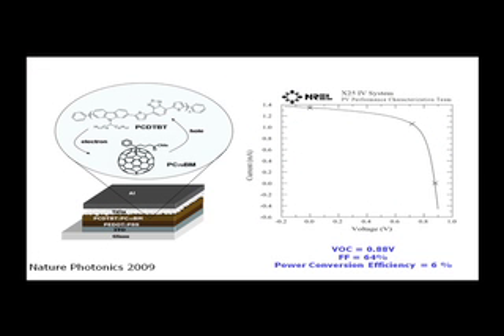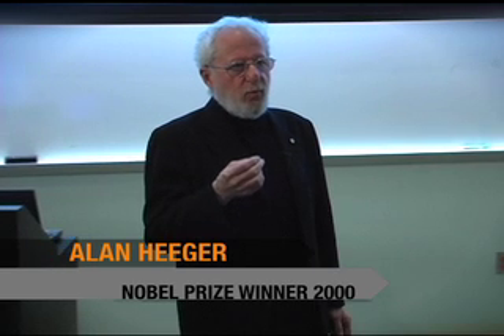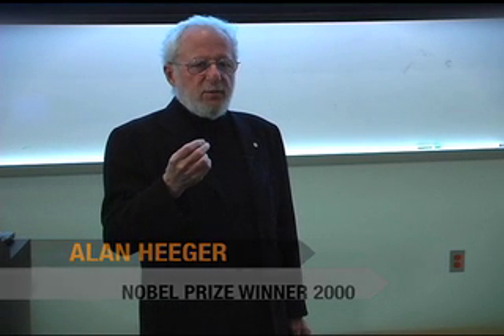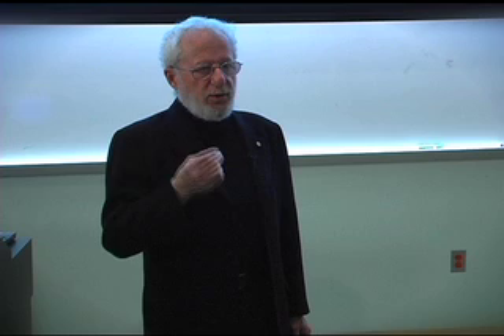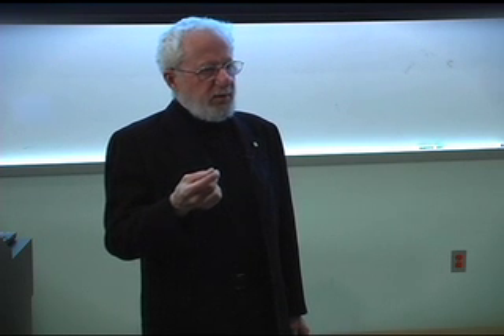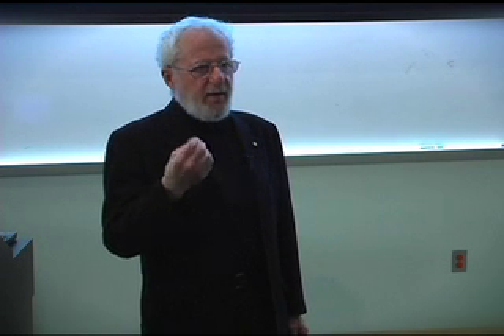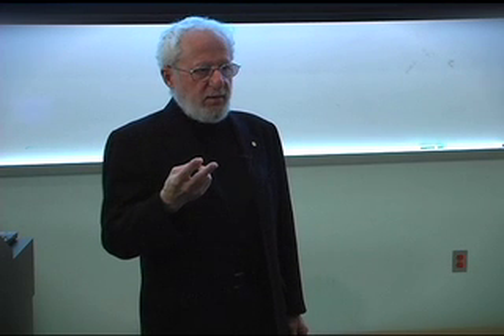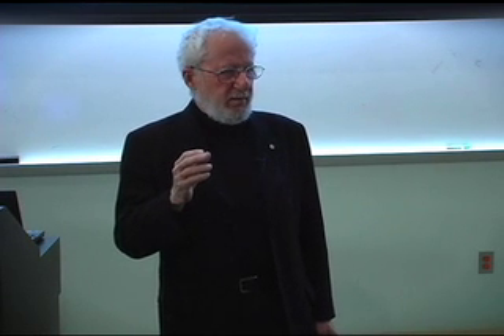Here's an example of some work that we did a couple of years ago. It gives us a 6% solar cell. By now, this is no longer a record breaker, but it's interesting because in this particular system, we were able to show that the internal quantum efficiency was approaching 100%. We could show that every photon that was absorbed gave rise to an electron-hole pair, and that we collected all of those. Now, not quite all, but more than 90%. And that's an important conclusion.